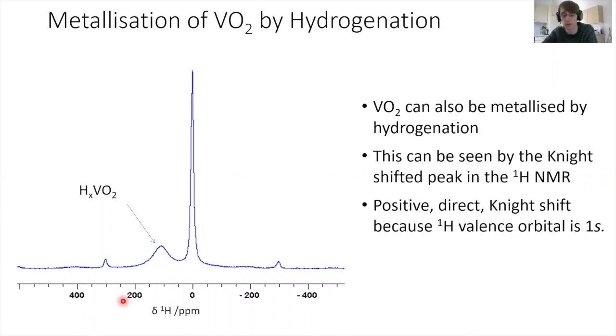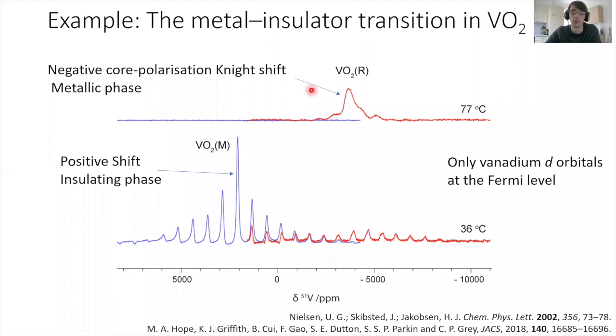It's on the order of 3%. And this was actually localized metallization. It didn't result in metallization of the whole sample. And so the vanadium spectrum actually looked pretty similar. If you hydrogenate further, then yes, you end up with a vanadium spectrum which looks more like this one for the fully metallized sample, except way broader, because you also have a distribution of metallizations. You have different local environments due to the protons. So it's negative, but it's less well defined.